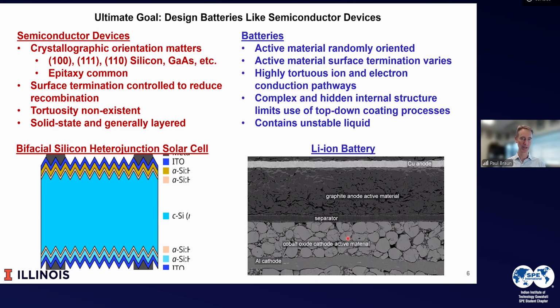So what I would argue is while batteries today have active material randomly oriented, the surface termination varies, there's highly tortuous pathways and a complex structure. And finally, it's filled with a thermodynamically unstable liquid. What we'd really like to do is to eliminate all of these problems and build it so that materials are not randomly oriented, control the termination, limit the tortuosity, simplify the internal structure, and make it more thermodynamically stable.